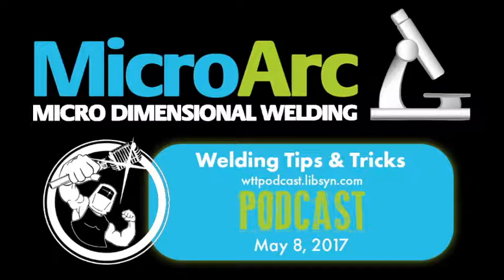It's a cold piece and you're popping that thing and it's solidifying immediately. Even though it was not putting a lot of heat in there, there was definitely some residual stress because it was bowing that little coupon up with just one tiny little bead across there. That's just something I observed with the testing we were doing. Really? Because I don't find that. Maybe we were doing it wrong. We were noobs, we just got a laser and said, let's weld some stuff.